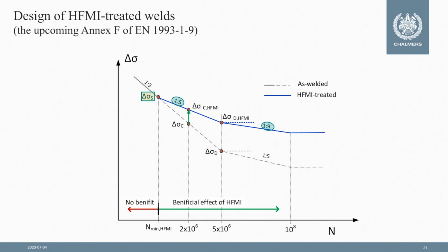At least theoretically, this is the point of intersection of the new SN curve for HFMI with the corresponding SN curve for as-welded details. And what this knee point is telling is that if we have stress ranges that are higher than delta sigma S, or in other words, we have a number of cycles that are less than N minimum HFMI, then we don't get any benefit of HFMI treatment. This is hardly the case in bridges, but in principle, this is the situation or a check that needs to be done, that we don't exceed this limit of delta sigma S then.